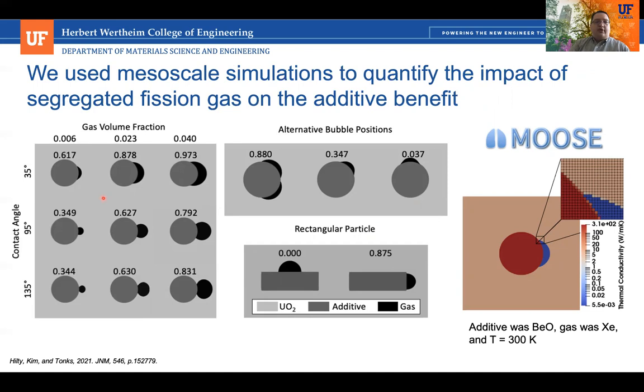And then we used a fission gas model to predict the formation of a bubble on that grain boundary with a different contact angle, which is going to be due to the ratios of the interface energies of the interface between the particle and the UO2, and also the surface energy of the UO2 and the particle. And so we get a range of different contact angles, and we looked at all these different contact angles. We have some with highly wetted and some that were much larger contact angles, and so the bubble did not significantly wet. And we looked at different gas volume fractions.